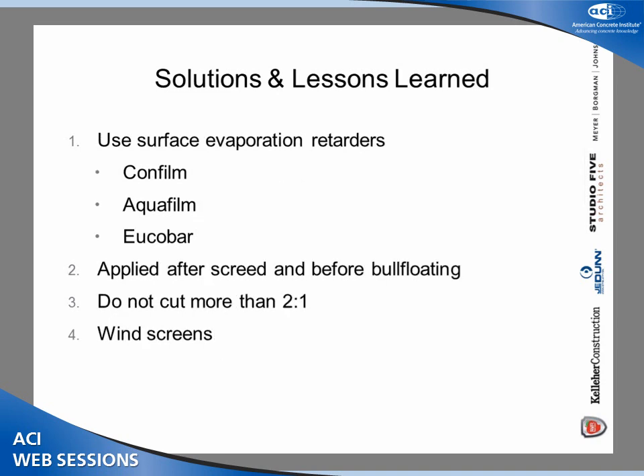The use of the surface evaporation retarders, such as Confilm, Aquafilm, Eucobar, we found to be very effective, especially on a wide module pan and joist deck where you have the deeper elements, the beams and the joist stems, which take a little bit longer to set. You want it to set bottom to top. And so that's where the surface crusting comes in. You've got to keep that surface alive, and these retarders do a great job of that until you can get that bottom to set top.